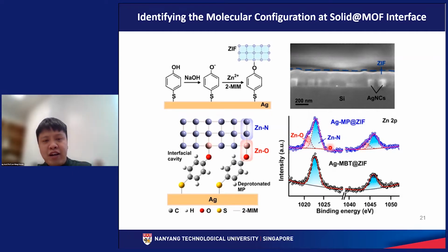So this tells us that our hypothesis over here is correct. On the other hand, if I were to use our previous configuration, whereby we graft MBT onto our silver surface, we expect no interaction between our MBT with MOF, and therefore there is only zinc nitrogen chemical environment in our XPS spectrum. So affirming this is important because this insight would tell us more about what is exactly happening to cause a change in the selectivity of the reaction.